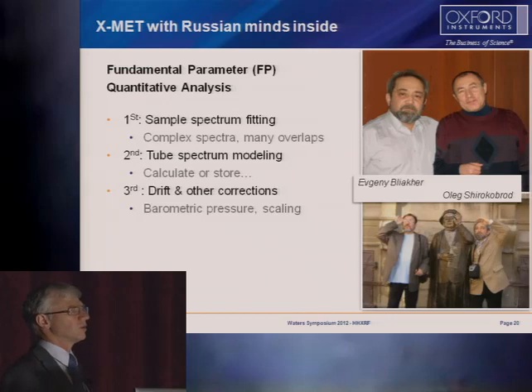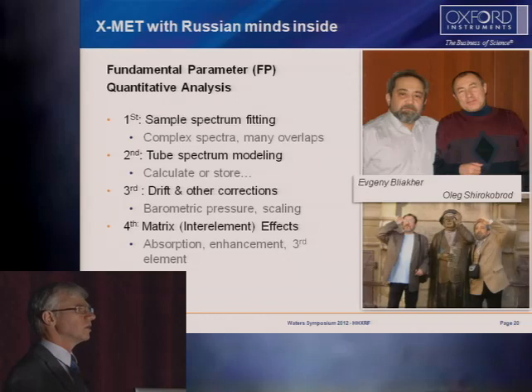Then there are a number of other corrections that needed to happen to make sure the intensities were good, and the thing that then you're trying to solve is the matrix effects, and they did that, incorporating all of the complexities, and that in a tiny low-power computer that fits basically in your hand, and it's got to be fast. Not like it was 15, 20 years previously when people were happy to wait for several minutes for the calculation to complete, which is what it took. It now has to happen with no delay. The overall measurement time is maybe 2 to 3 seconds.